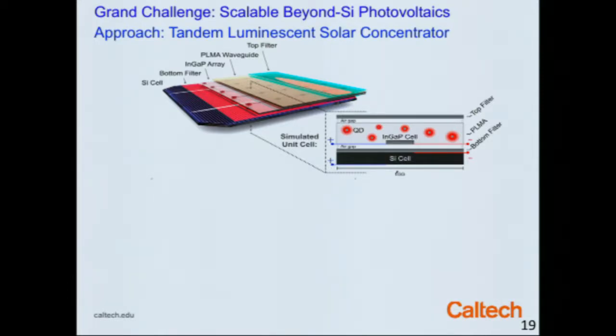The other feature are these highly luminescent 3-5, in this case indium gallium phosphide, solar cells. These are little microcells, hundreds of square microns, connected by a wiring network and embedded inside the polymer encapsulant. So this is the only difference between this and a normal silicon photovoltaic panel, which has that polymer encapsulant right there, is that it has embedded in that polymer encapsulant quantum dots and these small solar cells.